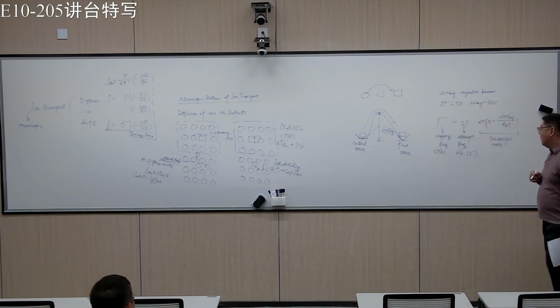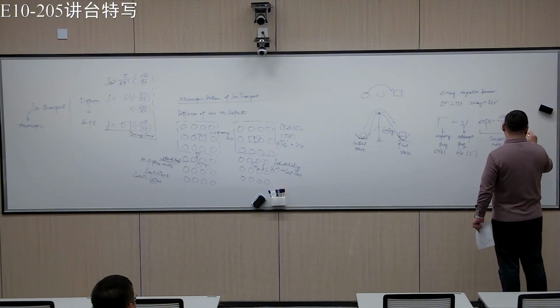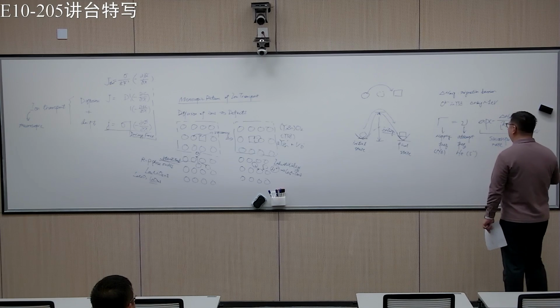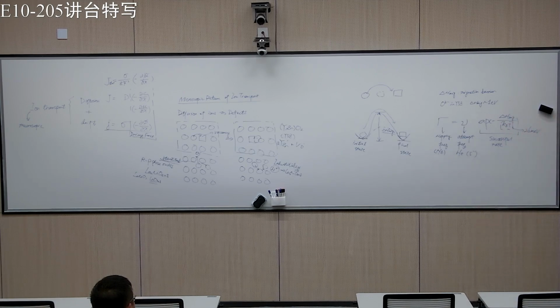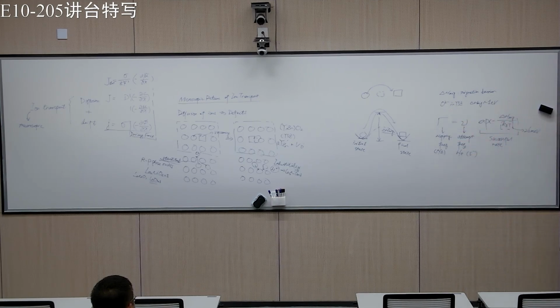We know that kBT is only 26 milli eV. So if you divide this by that, then take the exponential, you'll find the success rate to be very, very small. That is the reason why YSZ can only conduct oxygen ions at high temperature.